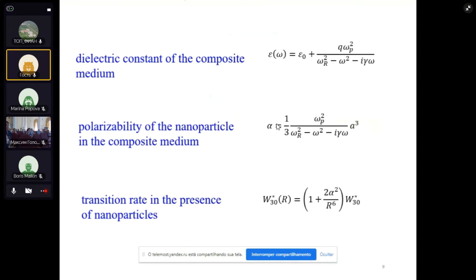So the model, as I mentioned, we work with the polarizability, with the complex dielectric constant of the composite medium, and the polarizability of the metallic nanoparticle in the composite medium. Transitions in the emitting species, as well as the index of refraction, will be modified, and they will depend on distance and the polarizability of the metallic nanoparticle. I'm not going into details, but these are the main points that we take into account from the theoretical point of view.